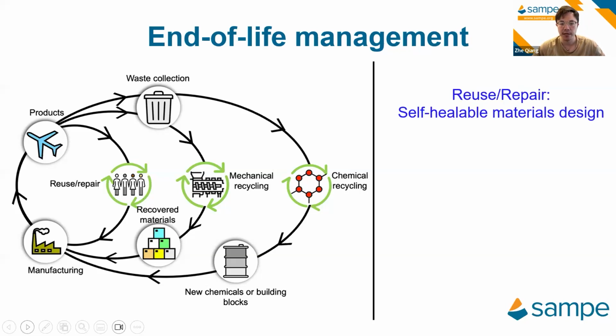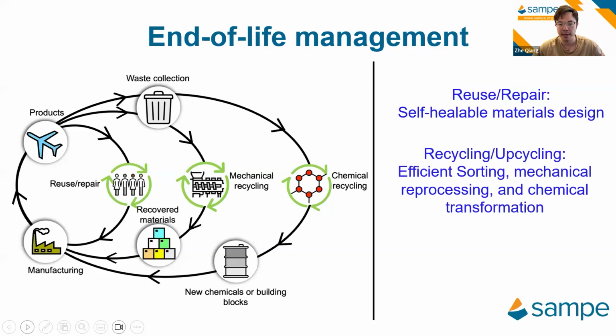But in that case, some of the crosslinked materials have to go through this cycle because they are not mechanically reprocessable. So again, to recap the end-of-life management, first, of course, we need to think about reuse and repair, which includes developing self-healable materials. And then we can think about recycling and upcycling. That also includes efficient sorting and separation of the materials, for example in carbon fiber composites. We need to separate carbon fiber from the composite matrix. Mechanical reprocessing and chemical transformation represent two general routes to extend the lifetime of these materials.